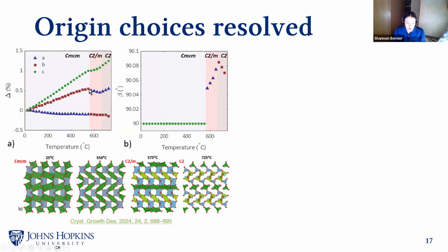There's a couple of other hiccups here, which are something that you're used to dealing with if you're a materials scientist, one of which is that the convention of which side of the unit cell is which changes when you go from one space group to the other. Specifically, the A and B definition changes, but I want to emphasize that if you were watching a specific atom that lay along the A axis of your original unit cell and it was going through a phase transition, it wouldn't teleport over to the other side. It would stay in one place. It's just the definition of our origin that has changed. So there is no crystallographic difference between these two, and that's why they're plotted in one line here. But if you were trying to compare to someone else's data and they had selected a different origin choice, it may look as though... Sorry, can I have a question?